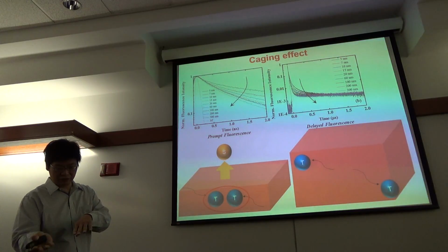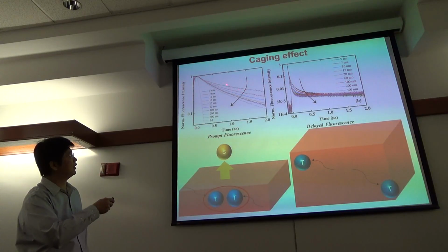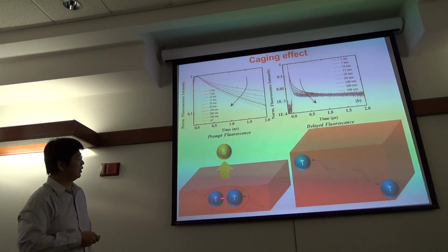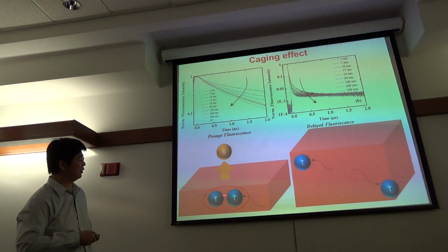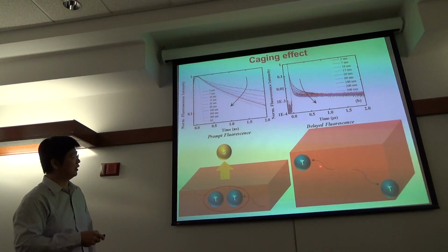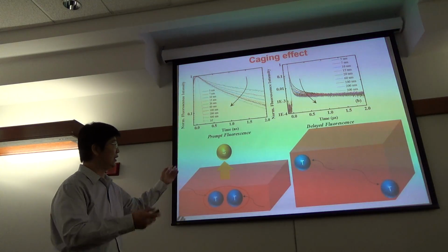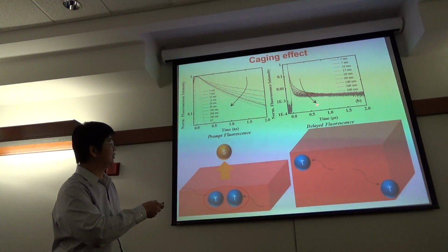That is the singlet to triplet, the triplet back to the singlet to give the light, and that is enhanced signal. So that we call the caging effect, because that is thinner, so the triplets will easily recombine and find each other and give the singlet. If that is very thick, they will go away and they will not give the light, so the intensity is lower.